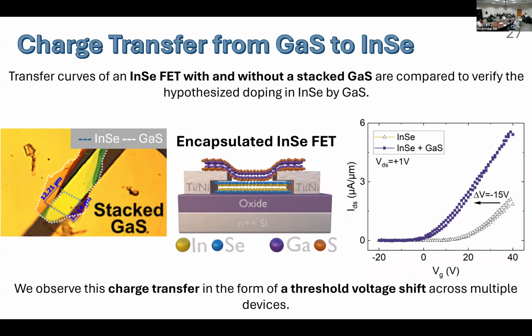So for the first type of device, where I have a pre-made indium selenide device and I stack a piece of gallium sulfide on top, I obtain the transfer curves displayed in the figure here. As we can see, the threshold voltage for indium selenide by itself is around 20 volts, whereas that for the heterostructure has been reduced by minus 15 volts to around 5 volts. So this is indicative of the charge transfer.